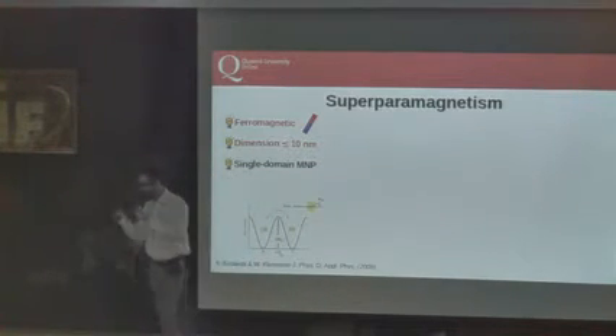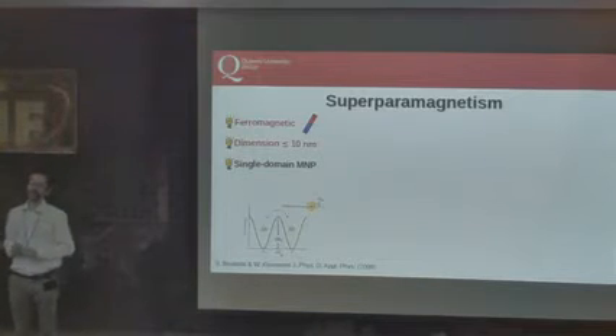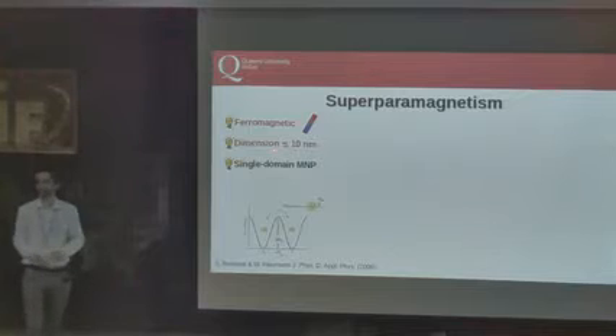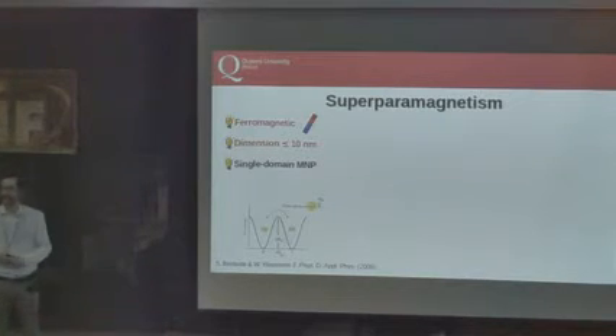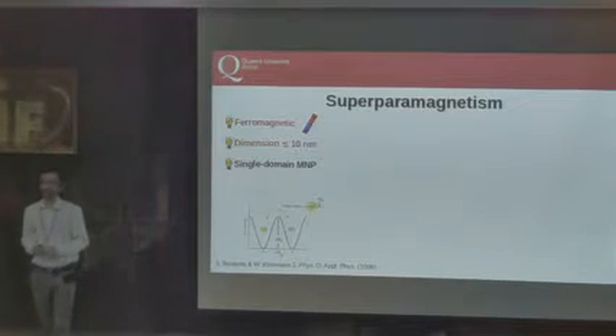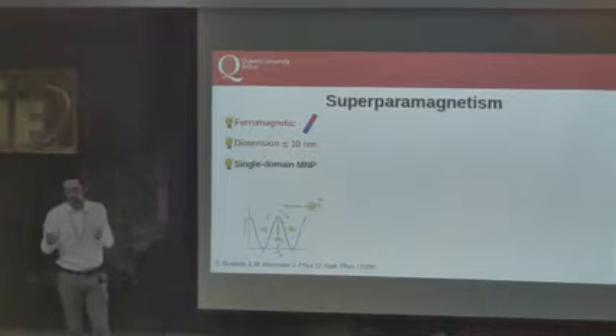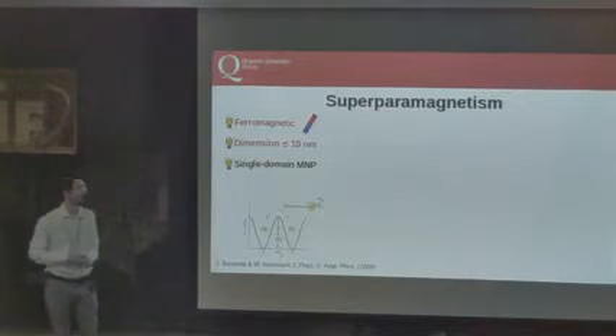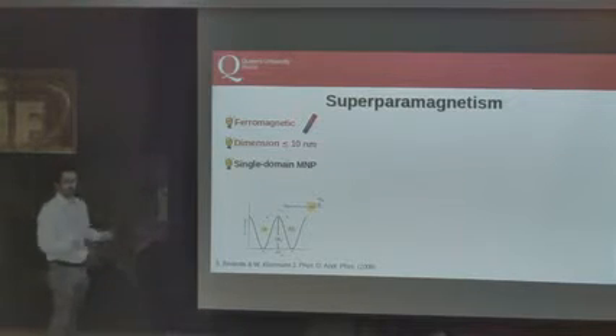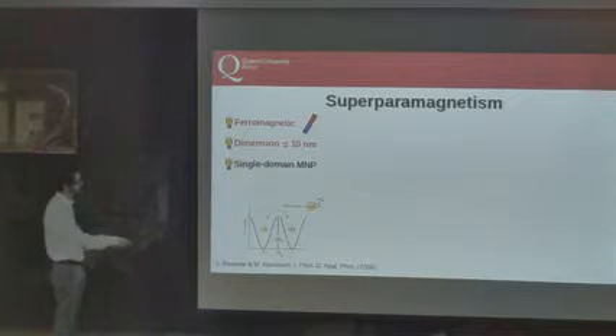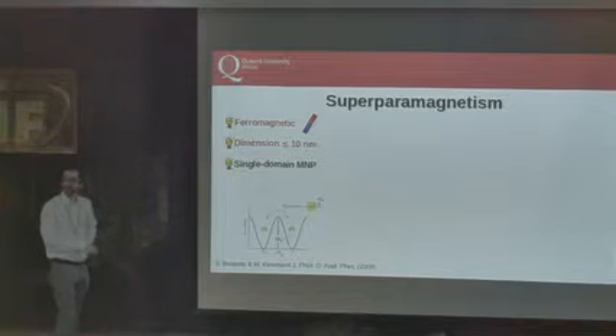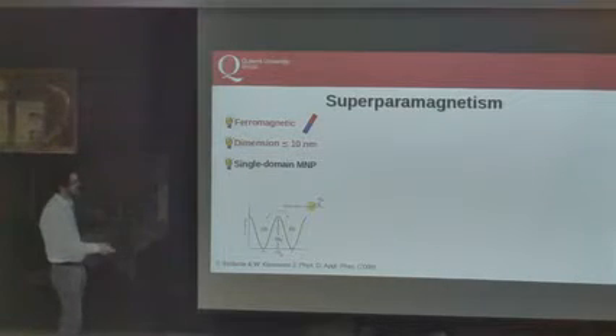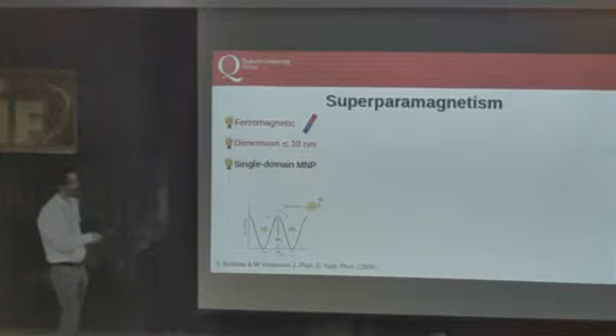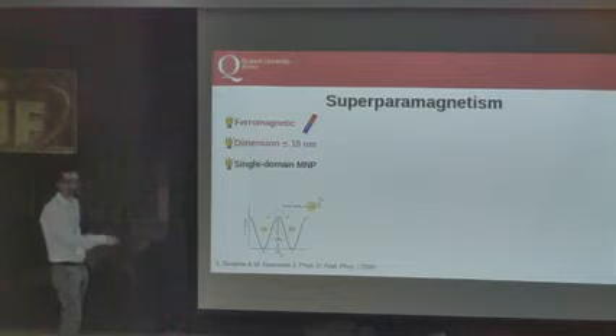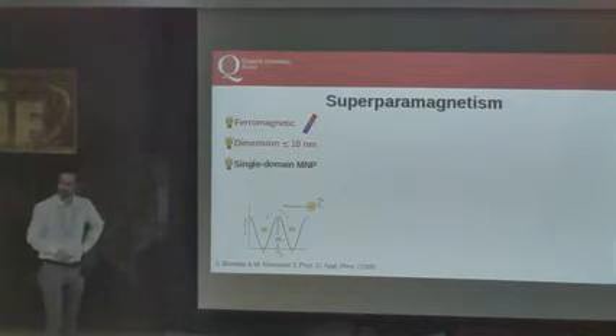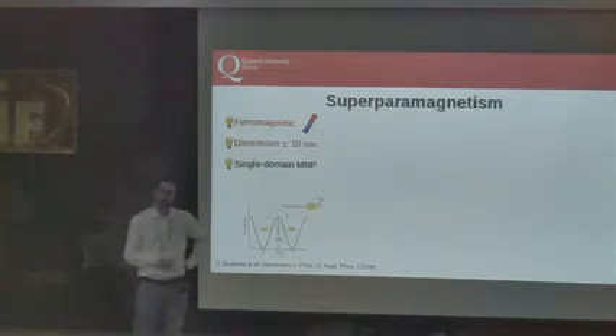Now, this is normal. We can think of very tiny magnets, but there is a rather peculiar property which manifests, in fact, for very small nanoparticles, which is called superparamagnetism. Now, we can think of the orientation of the magnets as the orientation which minimizes some energy. And in fact, there are two possible directions without external fields that minimize this energy. And here is the depiction. So there are two valleys. Let's say, just to fix the attention, that one direction which minimizes the magnetic energy is this arrow to the left, and the other valley is the arrow on the right. And without external field, they are absolutely the same.